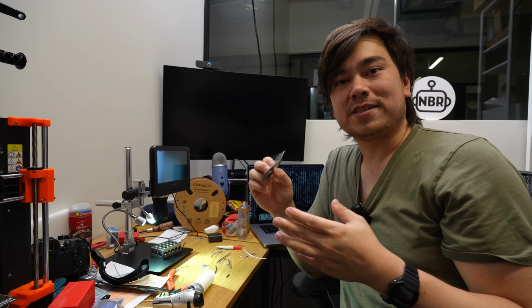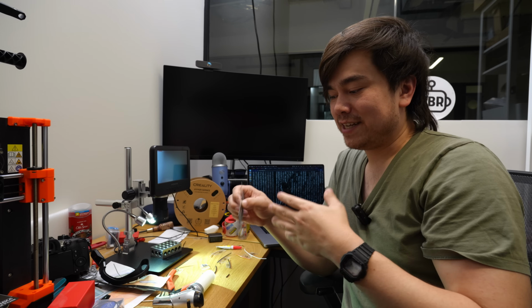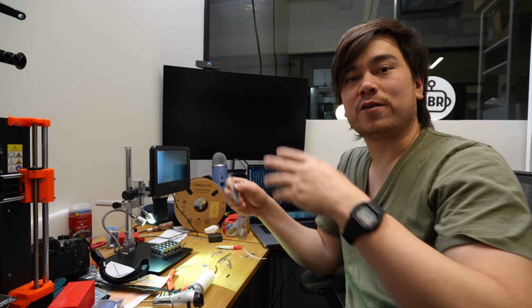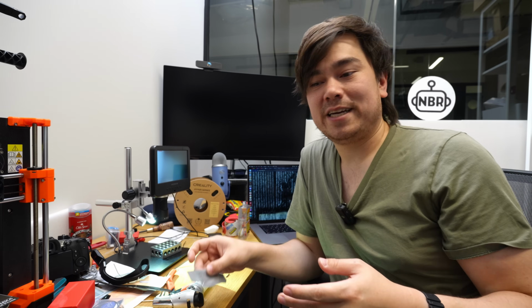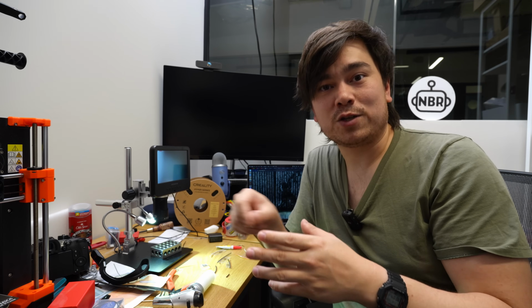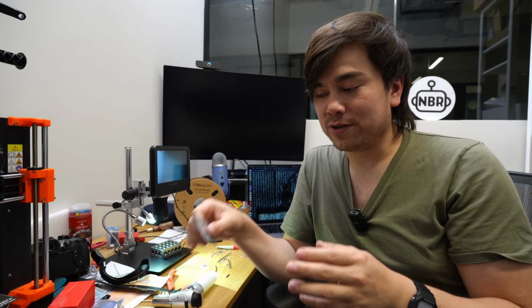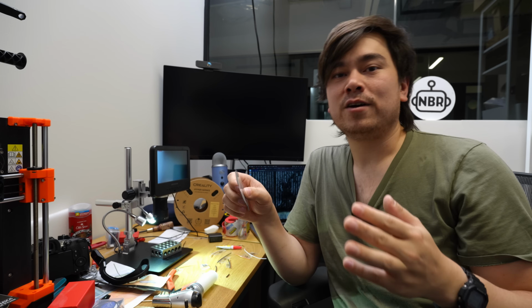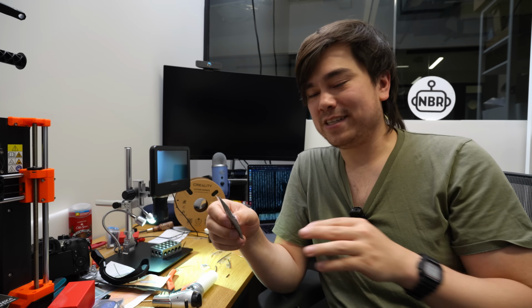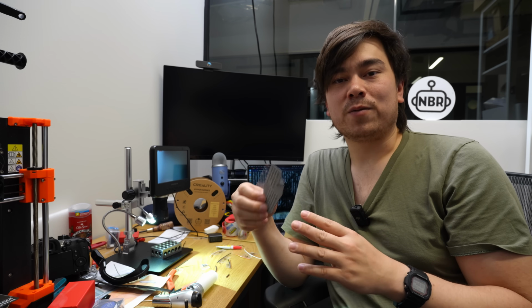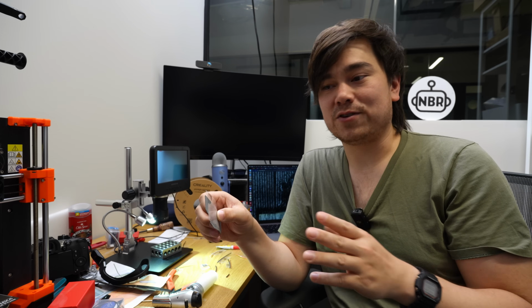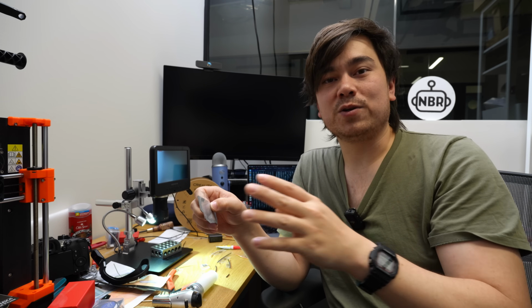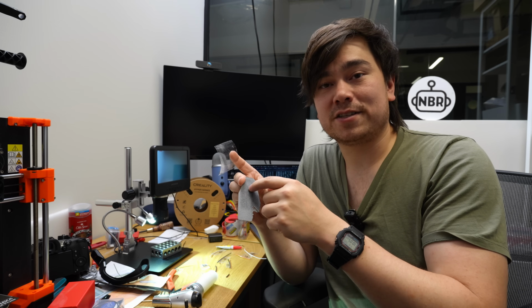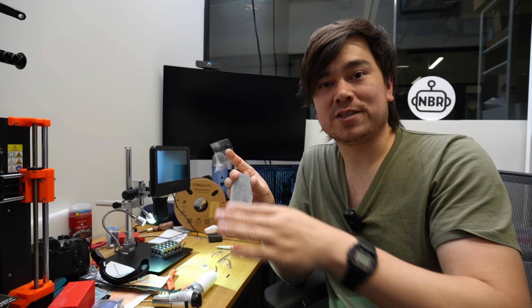Any of these powder-based processes I would also be concerned about, because basically they 3D print them and then they take them over to a bin where they try and get all the loose powder off. There's usually going to be some powder left over on the part. Now, if you spent more time in the sandblasting unit and getting as much powder off as possible, then sure, you could remove more and more of this stuff. But I think the better solution is to either clear coat or paint these parts, or as I saw in a factory tour at Xometry, they actually have a vapor smoothing machine, and that'll melt all the stuff on the surface of this part and get it to be one solid piece of plastic.